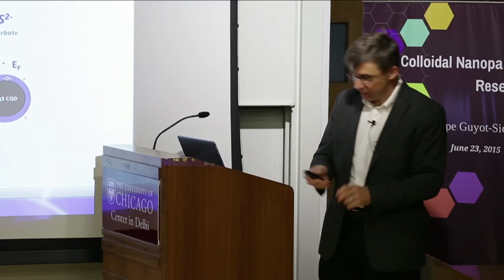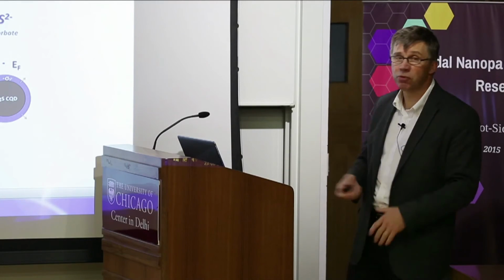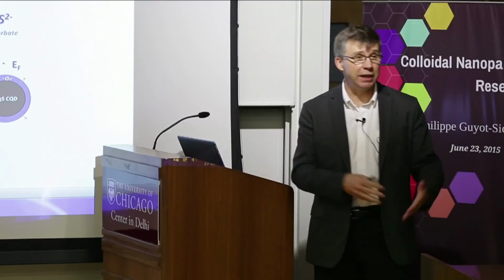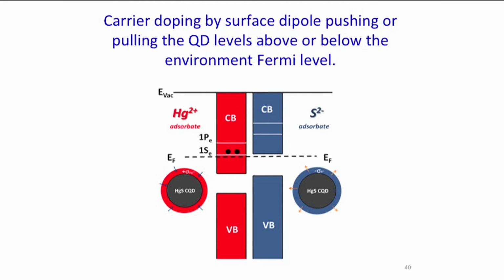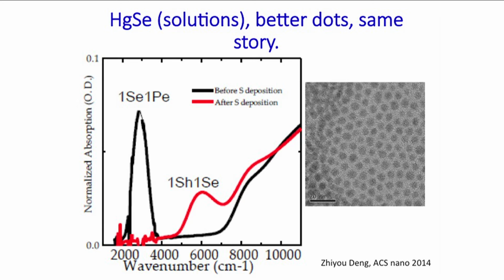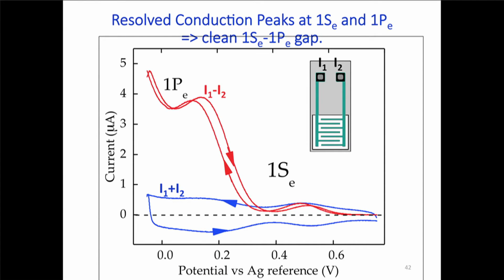And it turns out that the Fermi level of the environment, where the electrons reside in the environment, where they are available, just happens to be at the right position, such that we can move up and down with respect to that Fermi level, and electron transfers from the environment to the particle. So with the right condition, the right size of particle, and the right environment, we can have 2 electrons per dot. We studied also mercury selenide, same thing, better nanoparticle, better spectrum, but exactly the same behavior. And then we studied the conductivity of those things, the same way we did before with the cadmium selenide, and it works even better.